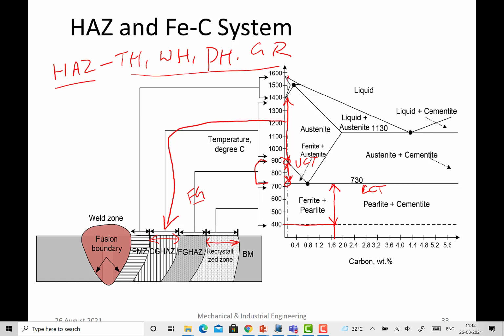Now coming to this zone where you have both solid as well as liquid, you can say the lower side has solidus and the upper side has liquidus. So the zone which is a mixture of both will lead to the formation of the partial melting zone. So in a typical steel having a little wider solidification temperature range, you will be getting all these zones, starting from base metal to the recrystallization zone, fine grained zone, coarse grained heat affected zone, and partial melting zone.